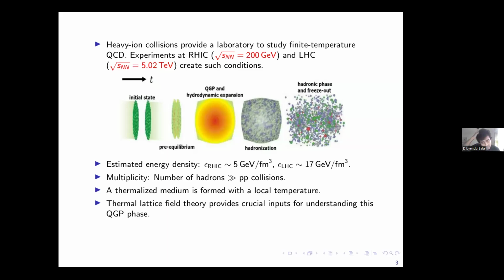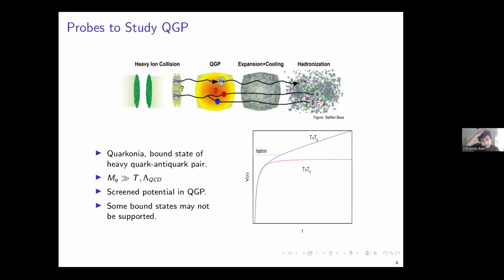Okay, so now I come to the main question: how do we study this system experimentally? For example, here is a cartoon. The probes are called quarkonia. Quarkonia are bound states of heavy quarks like charm and bottom quarks, and they are produced at the early stage of the hadronic collision because of the large amount of available energy just after the collision. Once they are produced, they propagate through the plasma, and through interaction with the plasma some of these particles will melt and some of them may survive. As a result, the number of particles that you would expect will be smaller.